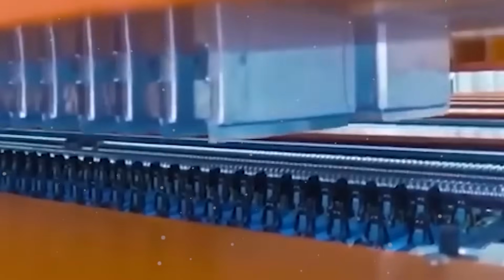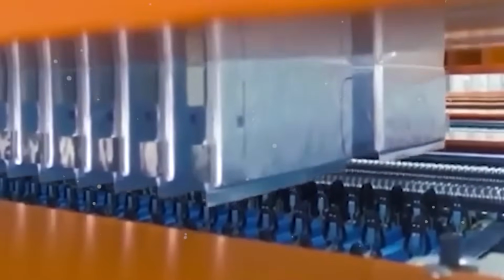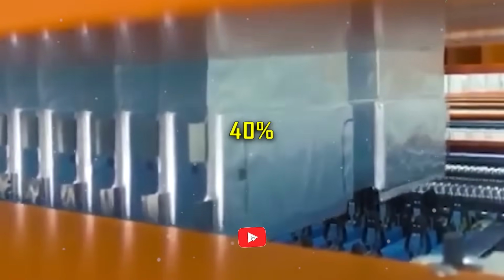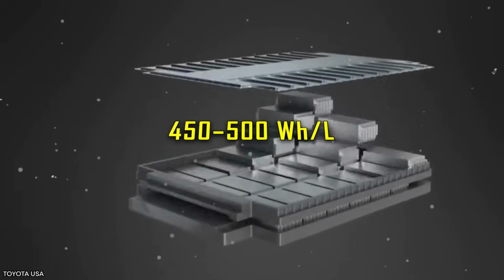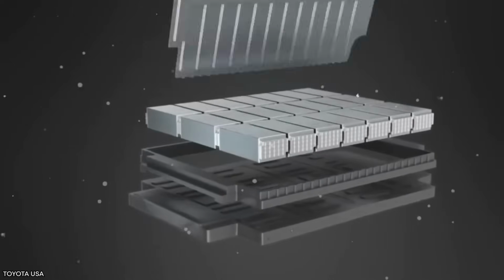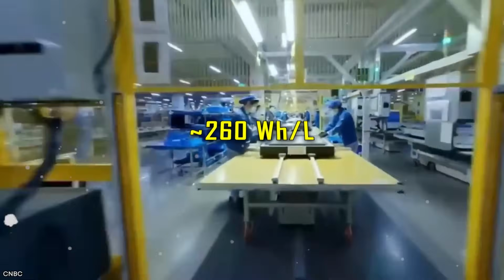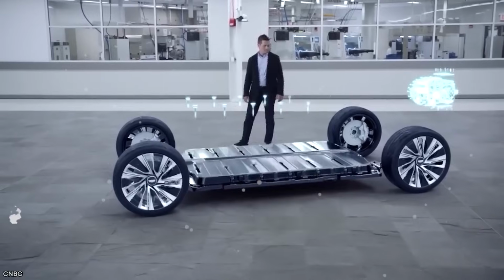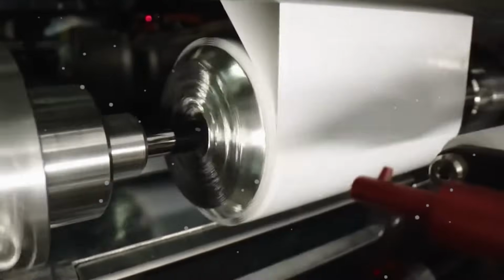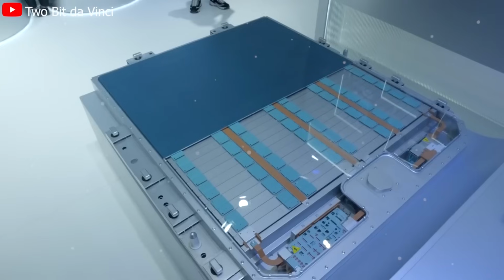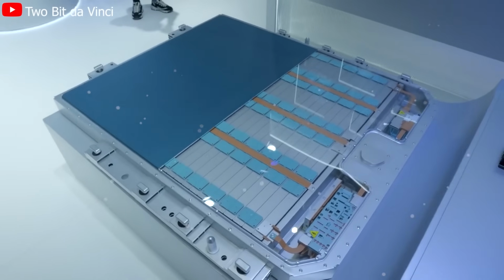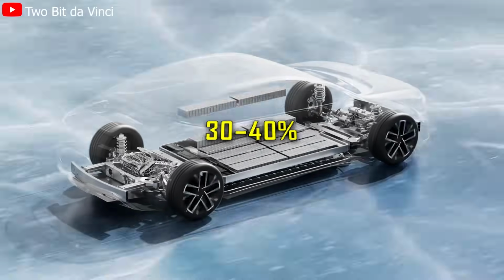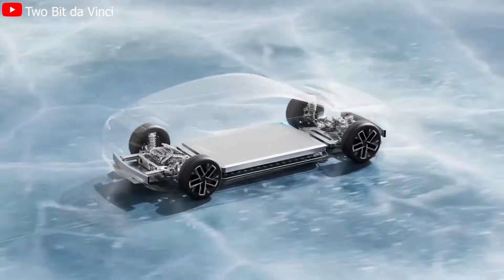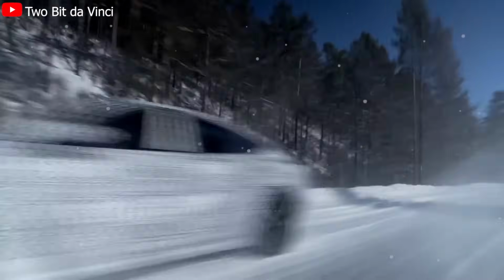The impact? Massive. Tesla can now reduce battery pack volume by up to 40%, while boosting energy density to upward of 450 to 500 watt-hours per liter. Compare that to approximately 260 watt-hours per liter for legacy lithium-ion and approximately 360 watt-hours per liter for the current 4680 cell. This allows for equal range in a smaller pack, or 30 to 40% more range in the same space. But range isn't the only gain.